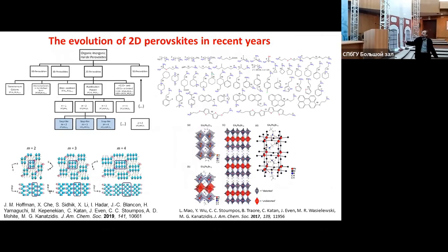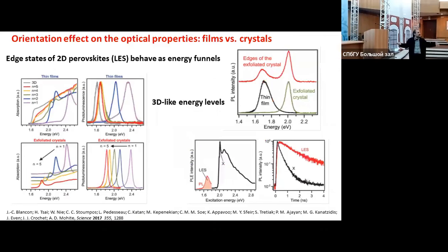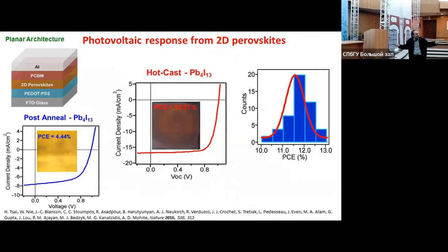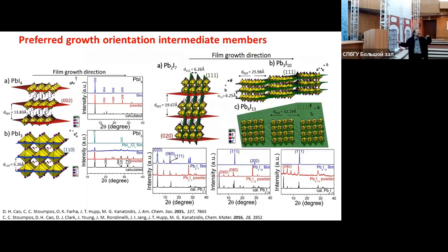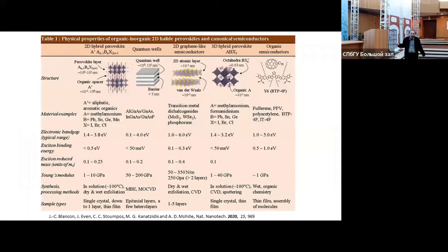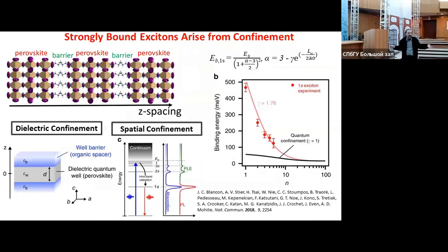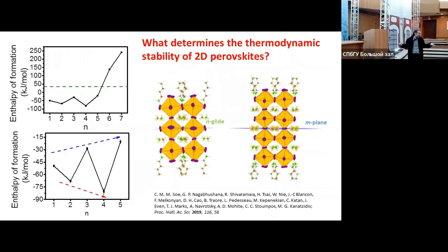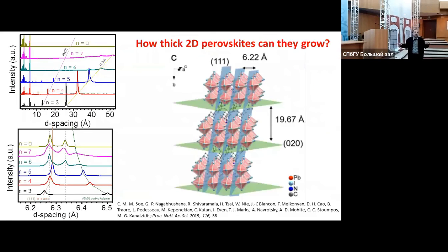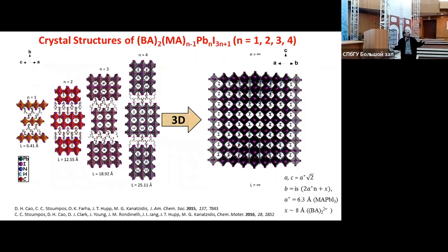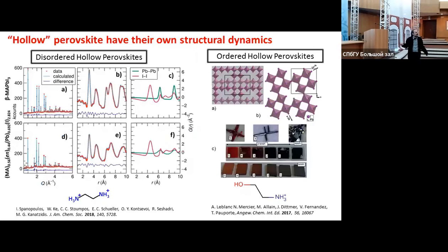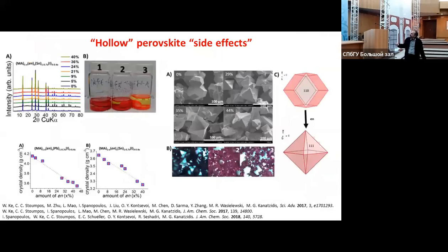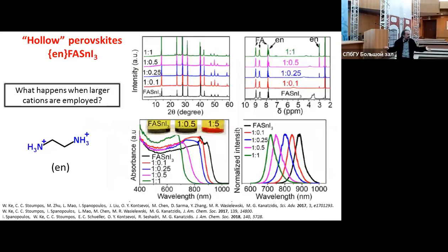So what is going on is that normally tin has the tendency to dope p-type by itself because of its self-oxidation. But if you stop the self-oxidation, if you block it, then you can make a perfect material without defects, which is merely intrinsic, but on the N-type side. But the mobilities, if you ask me what mobilities I measured, more than 1,000, but I don't believe that number. I would like to believe it was a wrong measurement. It's a very difficult measurement. But for lead that cannot be doped, for example, you get a mobility in the order of 100 centimeters squared per volt second. For tin, it can go higher. I hope I answered the question.